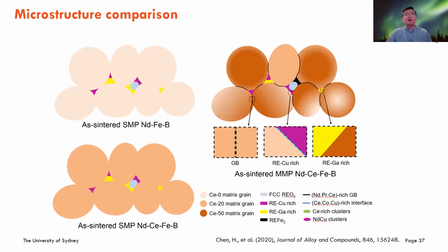And finally, we compare the microstructure of our as-sintered MMP neodymium-cerium iron-boron magnets with the as-sintered cerium-zero magnet, and also a cerium-containing one manufactured by the SMP. First we got some core-shell structures, but in some grains it's not that uniformly distributed. That's actually one future direction: how we can more accurately tune the core-shell structure here. Besides that, we did observe some cerium-rich phase, marked by black here, and also some clusters with cerium and copper, but no gallium clusters.